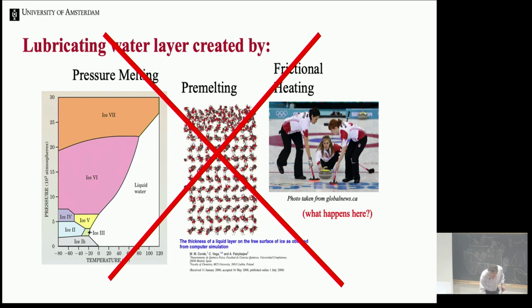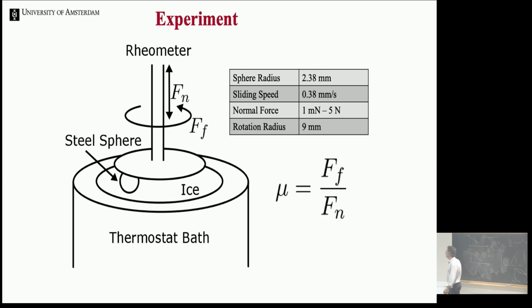Okay, so the experiment is deceptively simple. I have a rheometer, and it's actually only a rheometer head. And normally what you do, if you have a rheometer, you put a liquid between the rheometer plate and a bottom plate, and then you shear, and you measure the torque with which you need to shear at a certain speed, and that gives you the viscosity of the liquid. And if you buy a very fancy rheometer, it actually also measures the thrust that the liquid, if it's a complex liquid, might exert onto the top plate, and that is called the normal force.